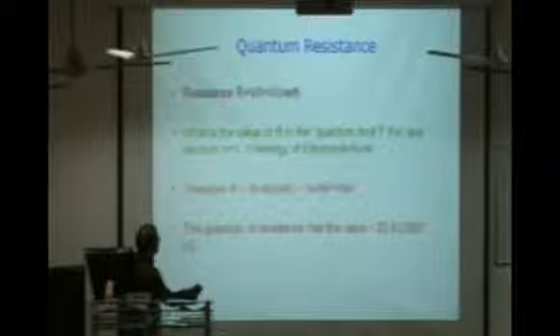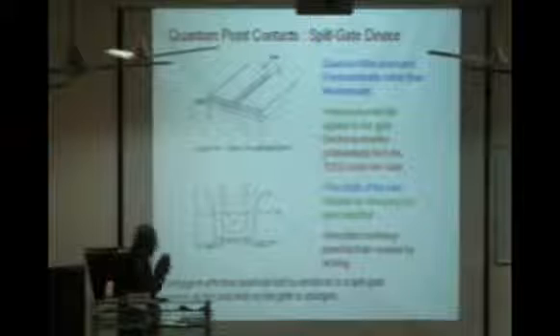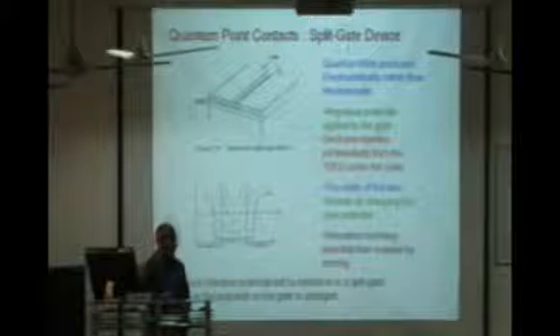and in fact we can define the quantum resistance something like this, and as you know this is the so-called quantum of resistance, which was first observed by von Klitzing in his experiment. This is called the von Klitzing constant. So the quantum resistance has a value of about 25.812807 kilo ohm, and this can be easily achieved in an experiment, which is not very difficult to do.